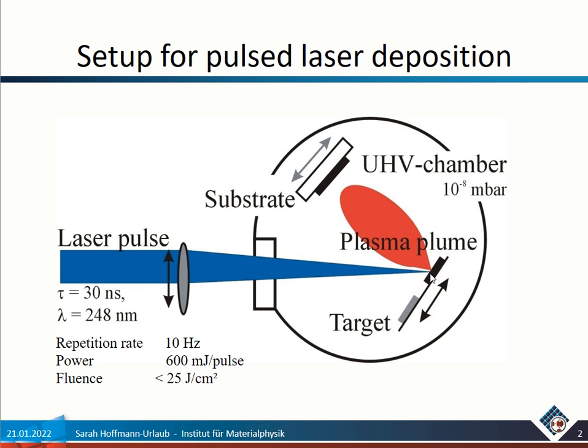In the chamber here, the laser beam is focused onto a target. In the chambers we can have multiple targets at a time, so you can deposit multilayers. The targets are moved, mostly rotated, but with chamber 1 it's only a moving procedure installed that tries to avoid the roughening of the target.